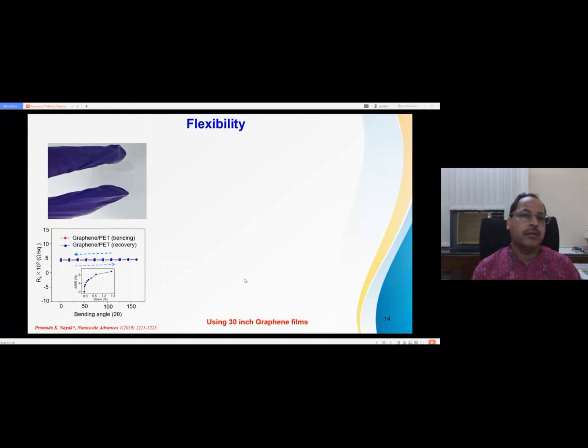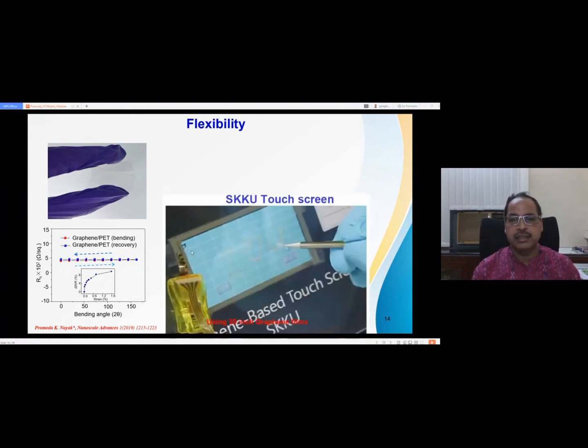So we have done the flexibility test also. Transfer the graphene on the flexible PET substrate, and you can see from the bending and the recovery cycle, there is very little change in the resistance. This is more or less remaining the same. Okay, so you can use it as flexible. So now the application you can see here.